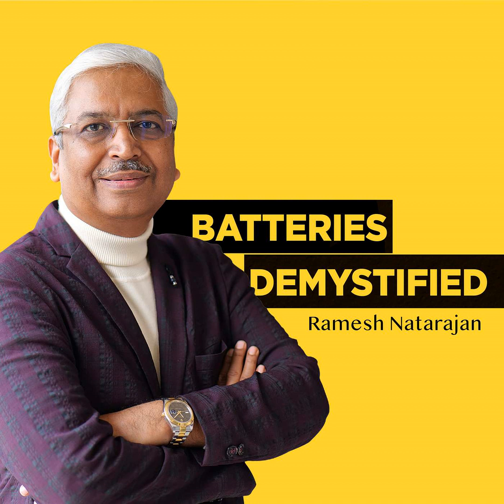Most of the people mix it with water because then the dispersion is uniform. Whereas when you do a dry mix, being very light in weight, it can go away into the atmosphere. Sure. So it's very similar to carbon. Of course, with carbon they do a dry mix, but with Vanisperse, I've seen many of them mix it with water, and that will work very well. It will dissolve readily. Absolutely, it works well. Anyway, once the paste is almost done, it's neutral. It's not acidic anymore. So I think that's okay.